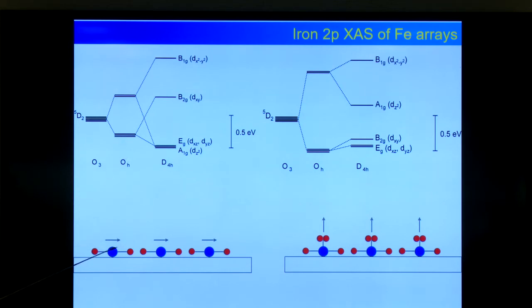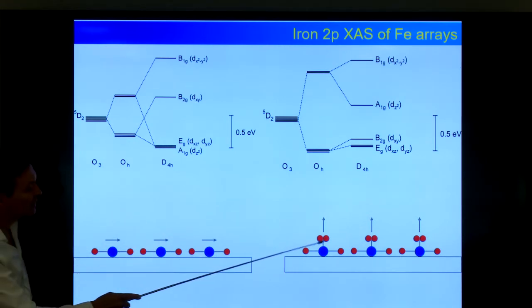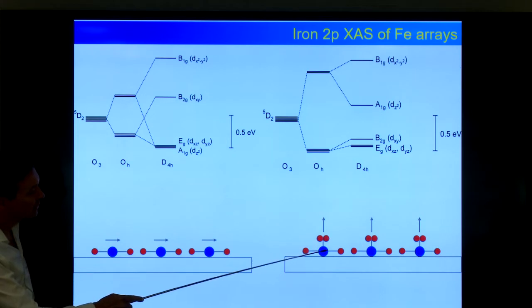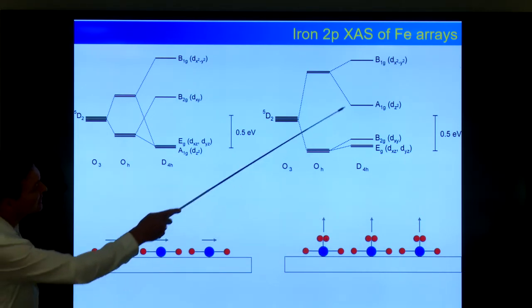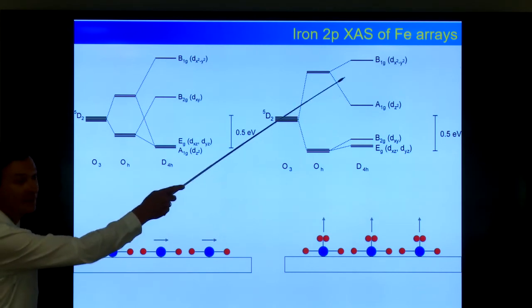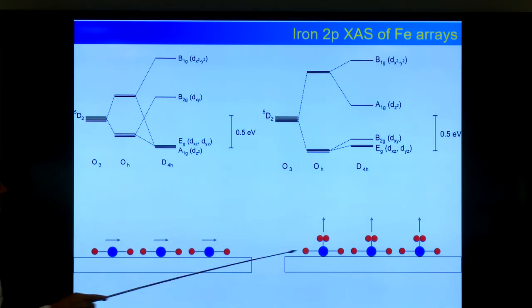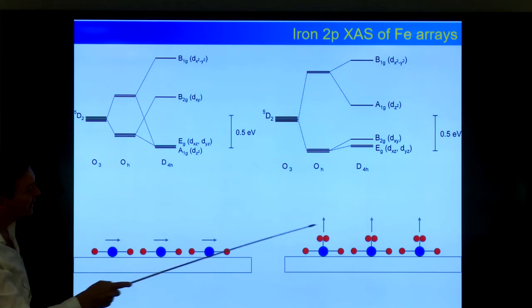So the initial system is oriented in plane. This is the iron in between the oxygens. And then if you let it react with oxygen at low temperature, the oxygen absorbs as a molecule, so it's not dissociated. It becomes more octahedral. You can see that the distortion goes down and you get a distorted octahedron. And the magnetic orientation goes out of plane.